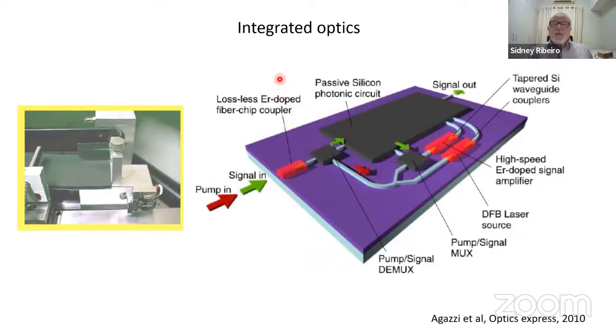You can also play with integrated optics. So you can prepare thin films, for example, erbium doped thin films, to have the optical amplifier at 1.5 microns. You can also play with the structure of the material in order to have a DFB laser. So you can have all these devices by playing with the sol-gel process. What you see here is a thin film deposited on a glass slide, and the image you see here is from an equipment where we measure the guided modes of the samples. You have light coming from the right here, and it's coupled in the film deposited on the glass surface, and you see the green light being guided by the film.